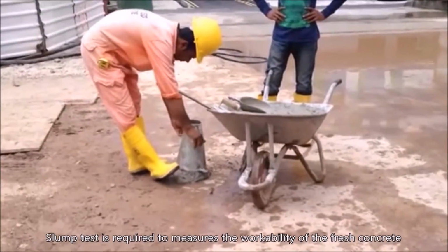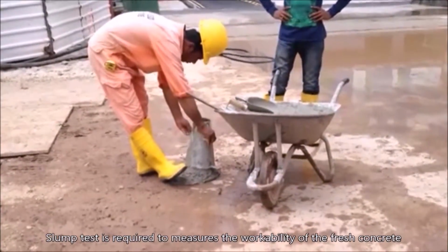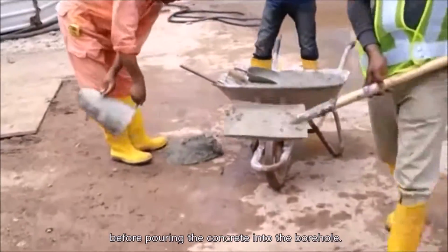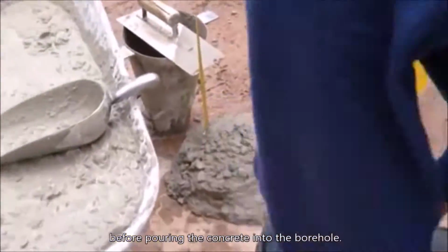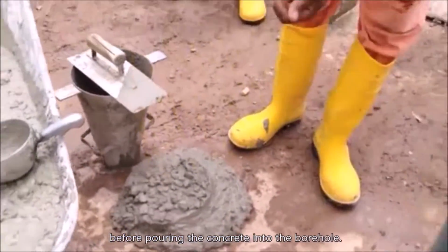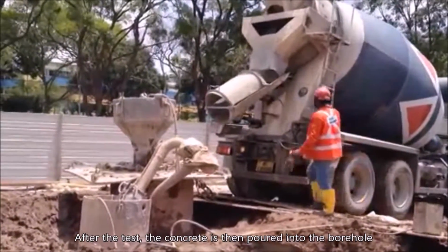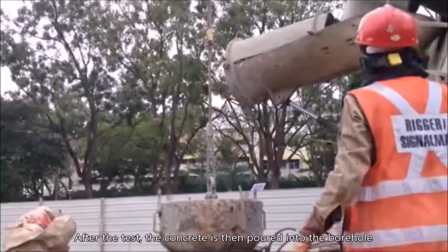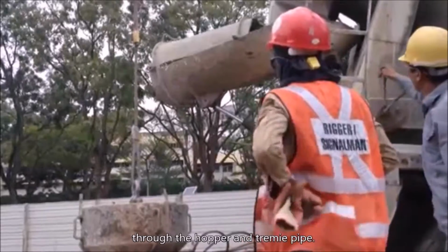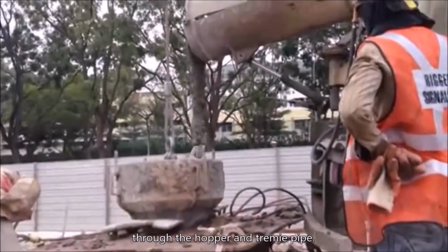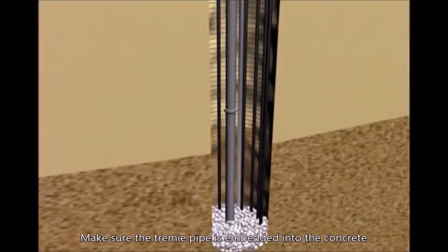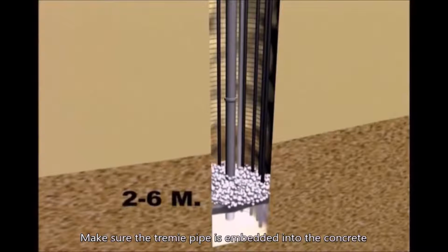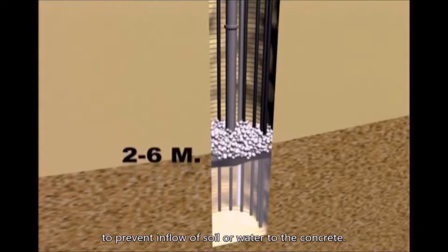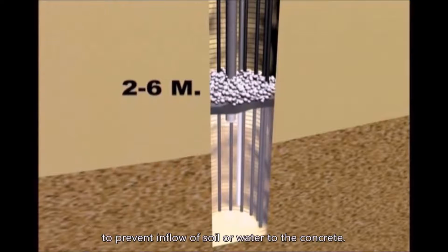A slump test is required to measure the workability of the fresh concrete before pouring it into the borehole. After the test, the concrete is poured into the borehole through the hopper and tremie pipe. Make sure the tremie pipe is embedded in the concrete to prevent inflow of soil or water into the concrete.